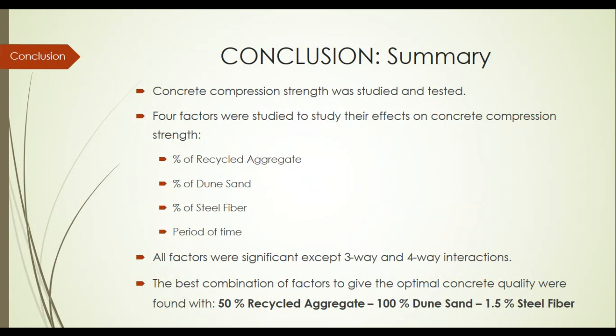So in conclusion, we can say we are able to come up with a new mixture that gives a good compressive strength, and we were able to identify the optimal values of these 4 factors. Our conclusions here are to use 50% recycled aggregate compared to non-recycled one, to use 100% dune sand instead of using the manufactured sand, and to add 1.5 steel fibers, and keep the mixture till 28 days, where it gives the optimal value.